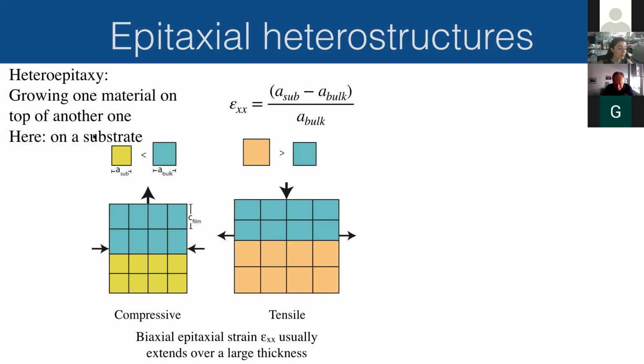So here we are growing on a substrate. Unfortunately for us, there exist very many different perovskite oxide substrates. So our perovskite oxide films grow nicely on top of them. So there are slight differences between the unit cells of the substrates we use and the films that we want to grow. And that's what this is supposed to represent. So if the substrate unit cell is slightly smaller than the bulk unit cell of the film you want to grow, then the unit cell of the film will be slightly compressed in the plane and it will expand a bit out of the plane. This is called compressive biaxial strain. And likewise, if the unit cell of the substrate is a bit bigger than the one of the film, then it will be stretched in the plane and compressed a bit out of plane.